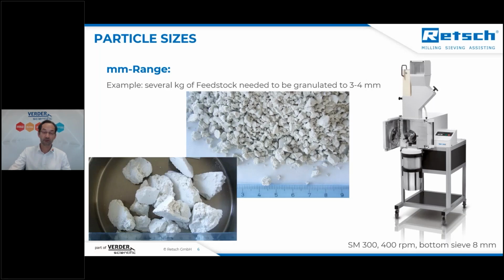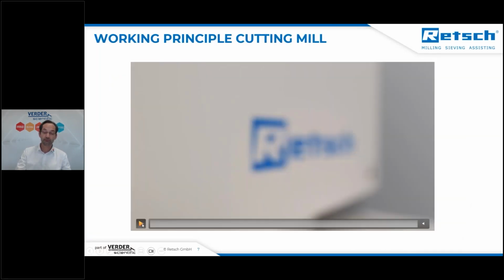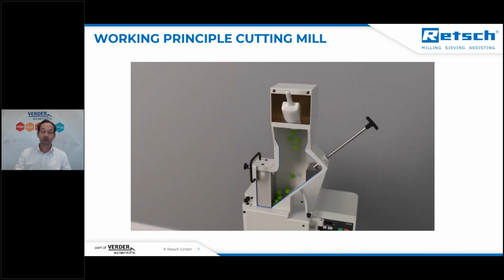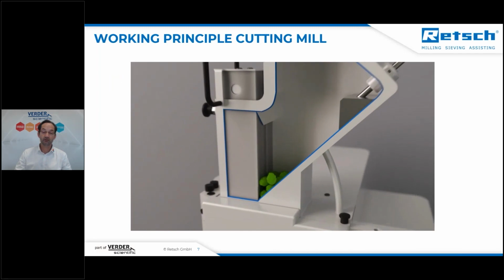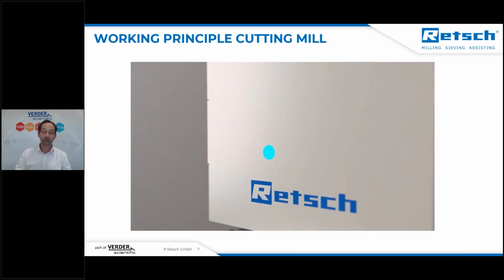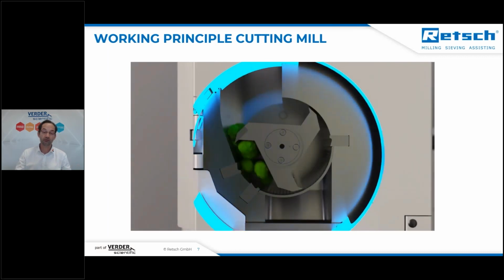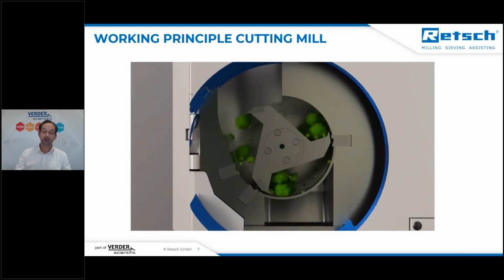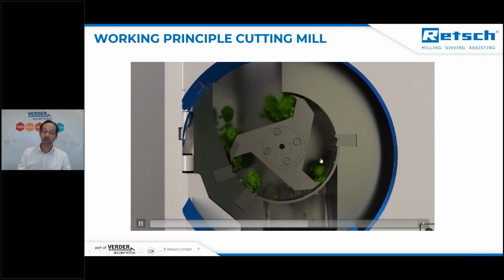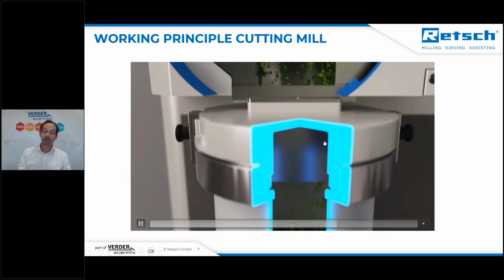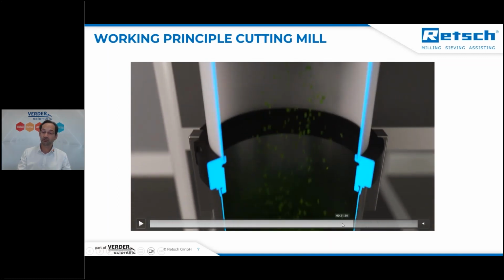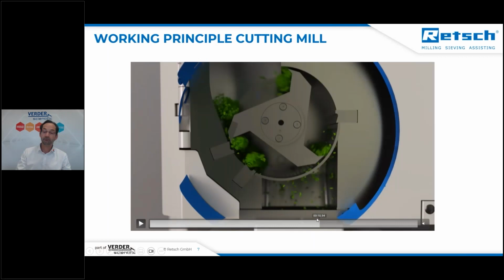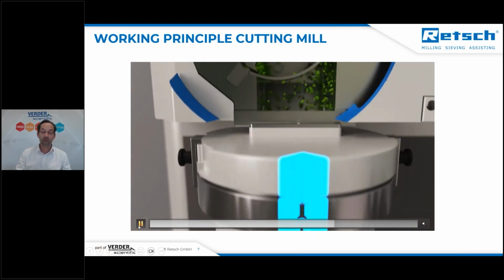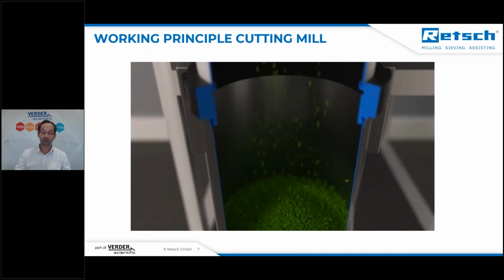So what happens inside the cutting mill? Here's a short video about the principle, where you can see the sample drops into the hopper, and then it enters the grinding chamber, where a rotor is rotating at a set speed. In this case, it was 400 RPM. And while the material is rotating, it is cut between the knives and the cutting bars. And this takes as long as it is fine enough to pass the sieve, which is placed in the bottom here, so all the material can drop down afterwards into the collecting receptacle from which it can be taken for the next step.